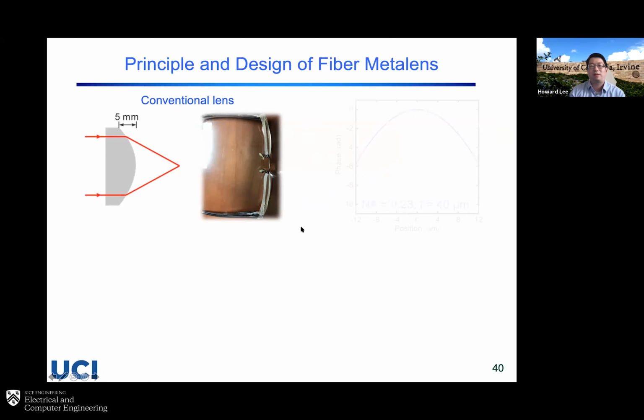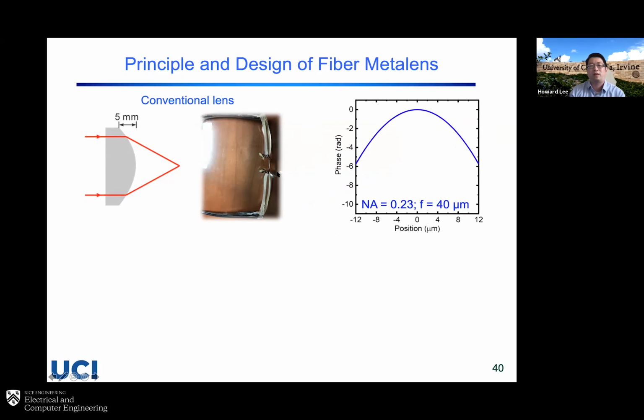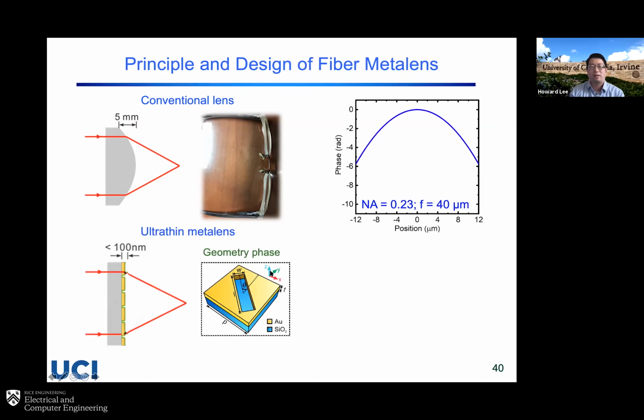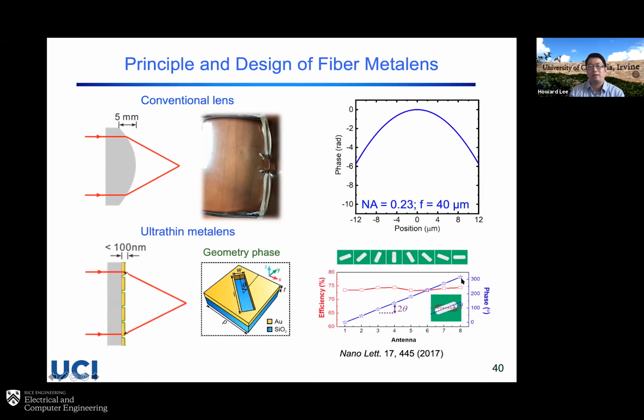But in order to make the lens, typically you need this kind of phase profile. That's why you need this kind of curvature here or different thickness to get the optical path to make this kind of phase profile to make a lens like this commercially. But then a metasurface lens will be like an ultra-thin lens, maybe 100 nanometer thick. And what we do to achieve this phase profile is use the so-called geometric phase. Using this kind of resonant structure, by just rotating this structure, we can achieve different phase. By rotating the angle, you can change the phase while keeping similar efficiency. So this is the trick of the so-called geometric phase metasurface. You can just rotate the angle to achieve the certain phase you need.